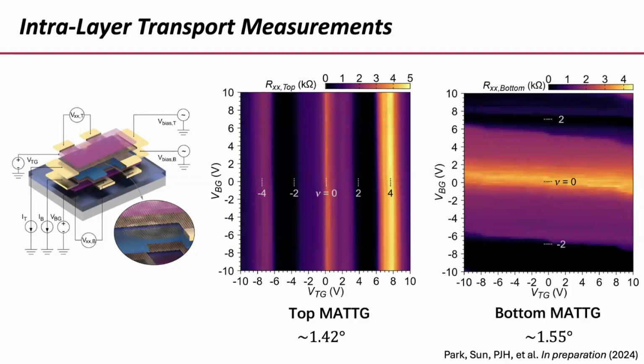And then if you look at the resistivity through the bottom magic angle trilayer graphene, you also have superconductivity here, and the charge neutrality point. This time the features are mostly horizontal because the top magic angle trilayer graphene screens the top gate. As you can see, there is a little bit of an angle, and we have less range with the back gate and with the top gate accessible. That's why you see only a portion of the phase diagram here. Now, there was a good reason to choose two magic angle trilayers, even though this is a very complex thing.